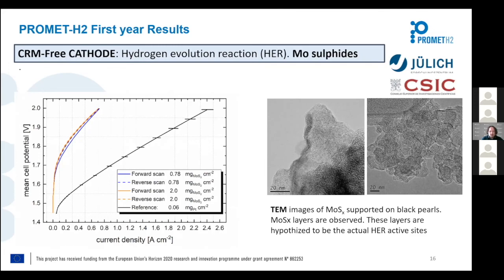One is 0.78 milligram per square centimeter, and the other is 2 milligram per square centimeter. We observe that we don't have so much difference, or it's not dependent on the loading we apply. It's clear that we still have a gap between the platinum group metal and the platinum group metal free electrodes.